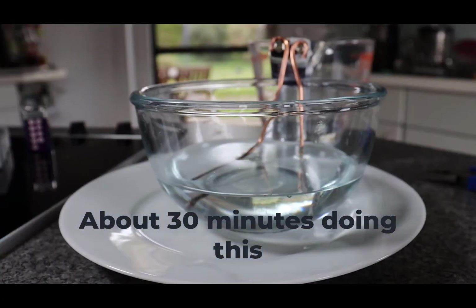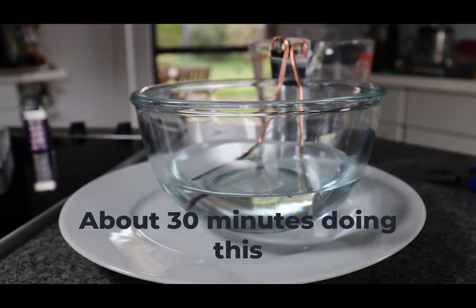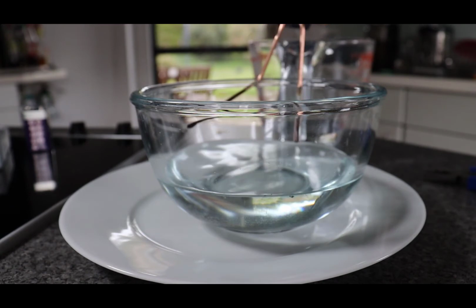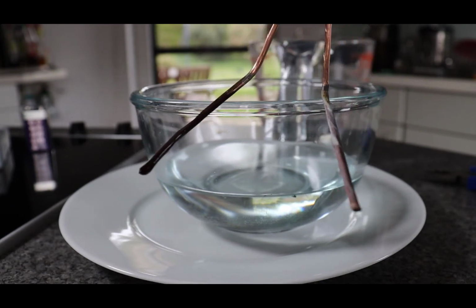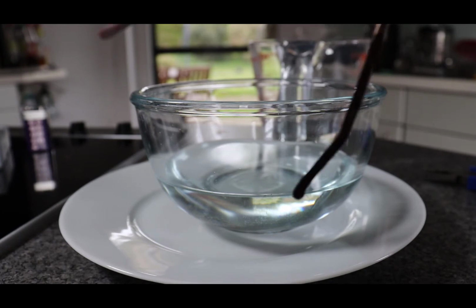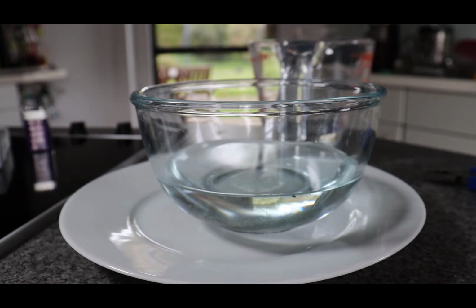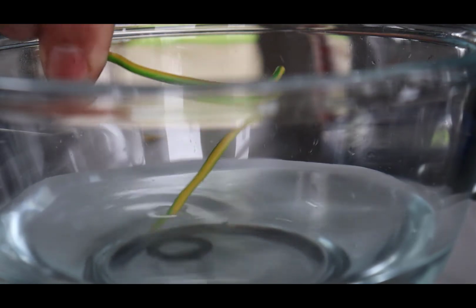So during this time, the electrodes are bubbling. It's quite difficult to get a nice sharp video of it, but the electrodes are bubbling. One of them is bubbling more than the other, and when I take it out you can see one of them is black and the other one is a funny colour. And while it was starting, a little pool of light blue colour built up around the positive electrode. You don't need to leave this for a really long time, because at some point the copper dissolving from one electrode goes and sticks to the other one, so you don't really gain anything anymore. As you can see, it's a very light blue colour, and I'm going to throw a zinc plated washer in there. I think it's a spring washer, and leave it for a bit.